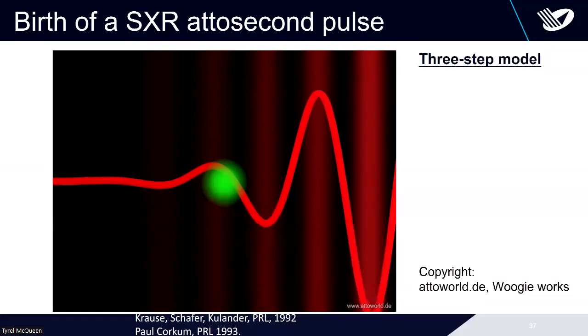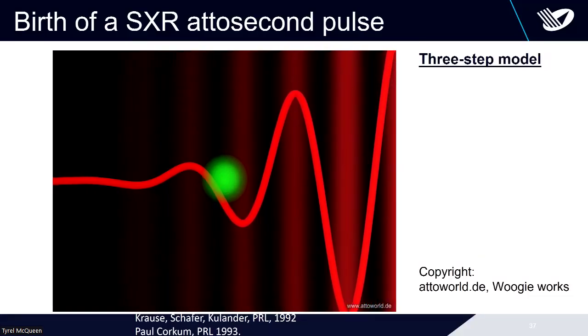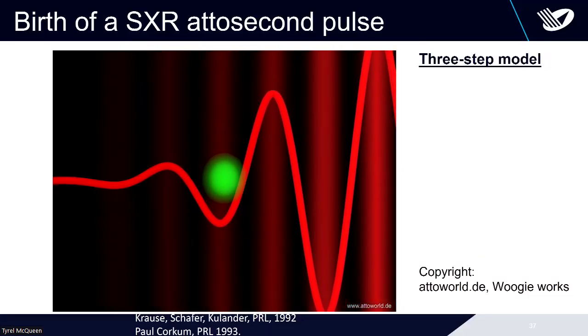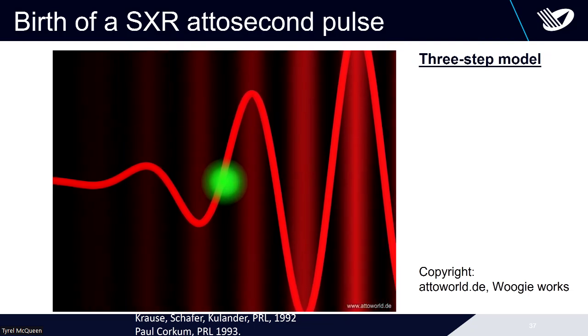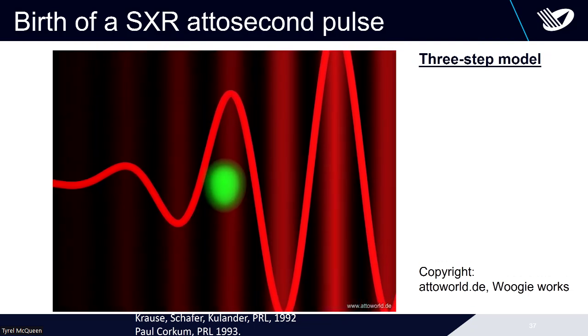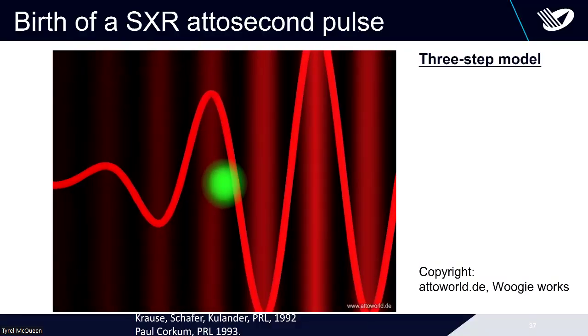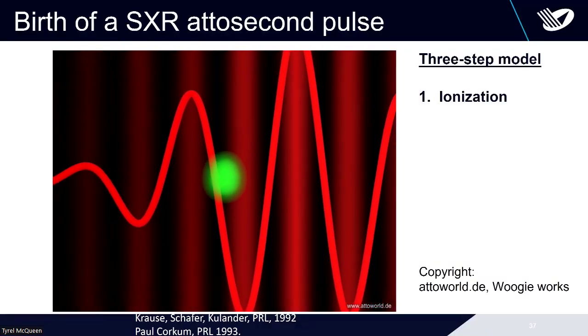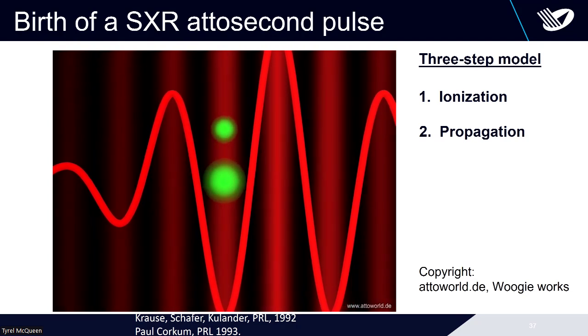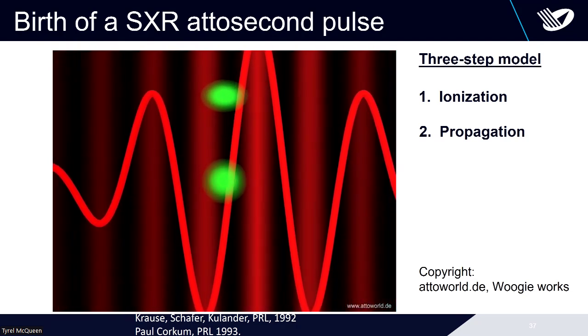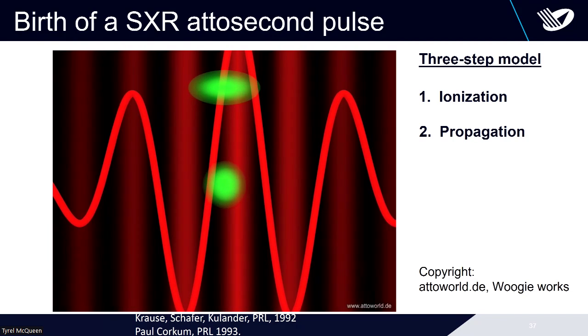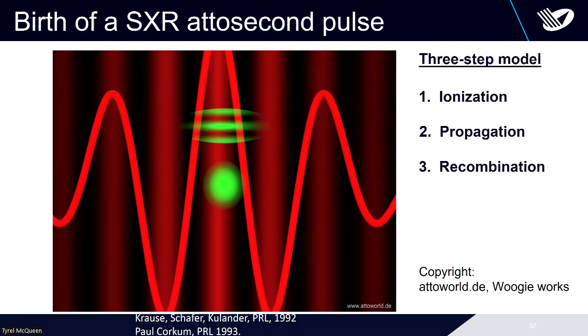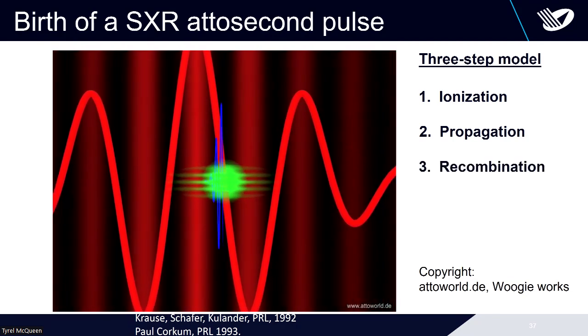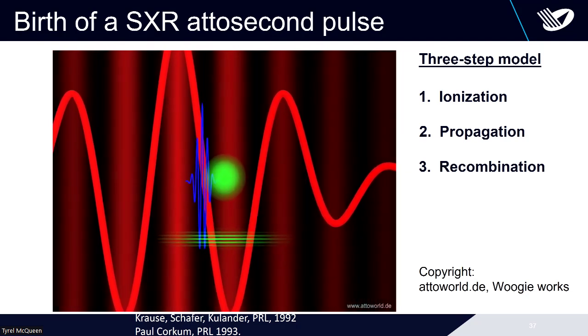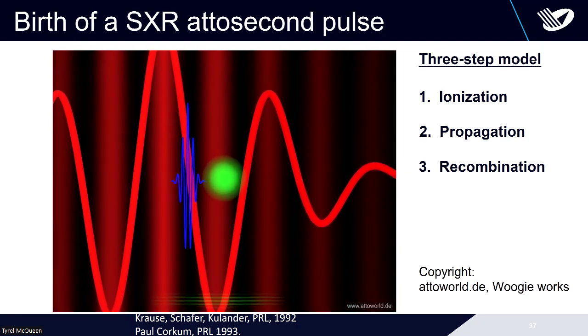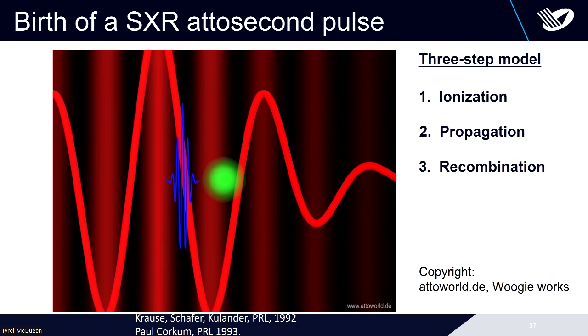Now, this is a very strong pulse. At the peak, it is on the order of the Coulomb potential of the outermost electron. So it starts really pulling and pushing on the outermost valence electrons. Once the field is strong enough, the Coulomb potential gets bent so much that the outermost electron can tunnel out into the laser field. Once the field changes sign, the electron can come back. It's accelerated more, and upon recollision, all the energy picked up in the laser field is released in the form of light. And that's the soft X-ray pulse that comes out.